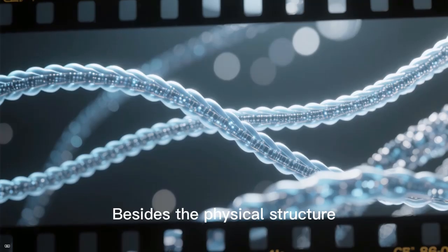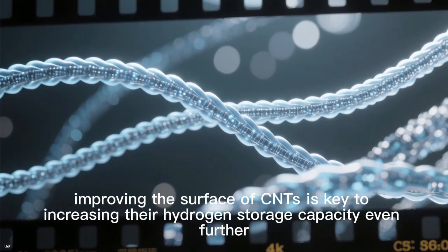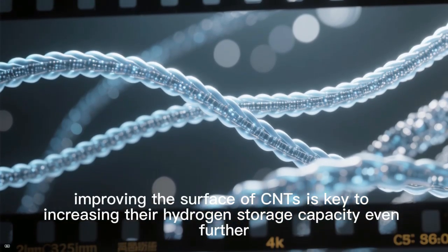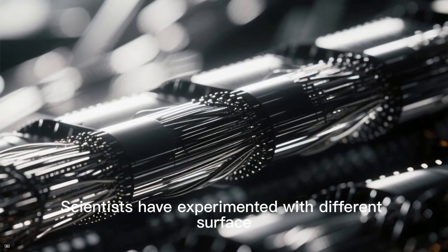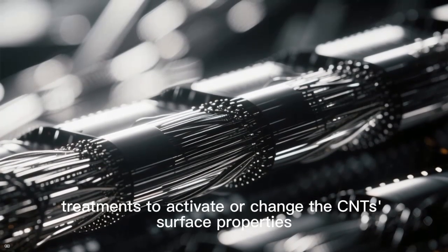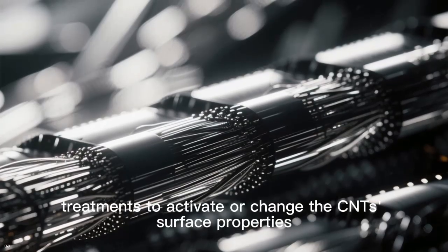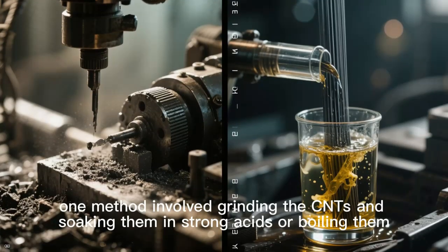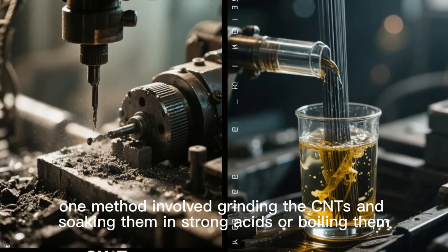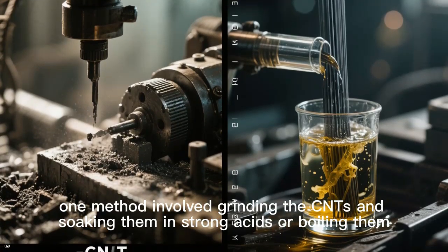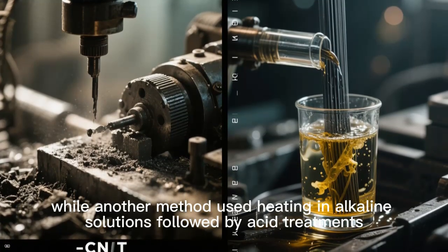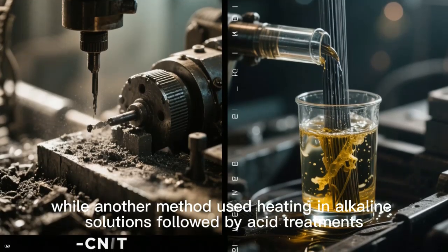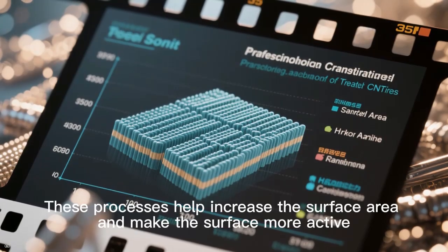Besides the physical structure, improving the surface of CNTs is key to increasing their hydrogen storage capacity even further. Scientists have experimented with different surface treatments to activate or change the CNT's surface properties. For example, one method involved grinding the CNTs and soaking them in strong acids or boiling them, while another method used heating in alkaline solutions followed by acid treatments. These processes help increase the surface area and make the surface more active, which allows CNTs to absorb more hydrogen, up to about 5% by weight in some cases.